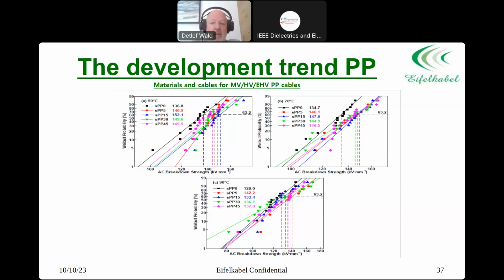Additionally, looking now again at mixing, there should be a slide before. Sorry, there is a slide missing. It somehow disappeared when I prepared it. At a different temperature, looking at the AC breakdown of polypropylene mixed with syndiotactic polypropylene. So just mixing isotactic and syndiotactic polypropylene up to 45% syndiotactic polypropylene. And here you can see the differences at different temperatures.